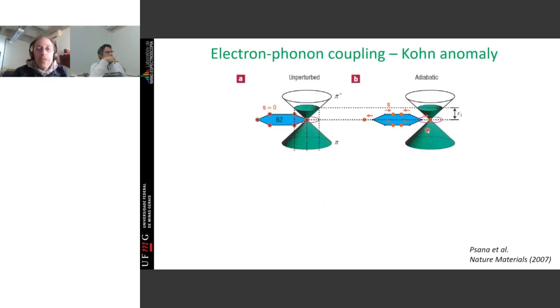This has to do with the so-called breakdown of the adiabatic approximation. So what's the adiabatic approximation? Usually we treat the electronic structure that is represented by this cone differently from the phonon structure that is represented by the atoms moving here. So in the adiabatic approximation, you say that when the atoms move, the electrons, being much faster, thermalize and do not care about the movement.